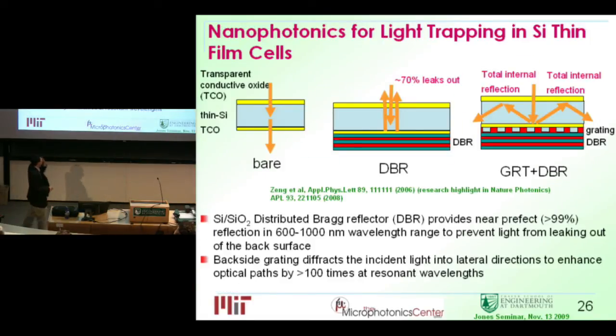So here's the approach we propose. If you do nothing, the light will only go through one path. If we have a perfect reflector, this distributed Bragg reflector, I'll talk about more detail in the next slide, you can get 2 paths. But as you get to a second pass, 70% of the light will leak out of the front surface again.